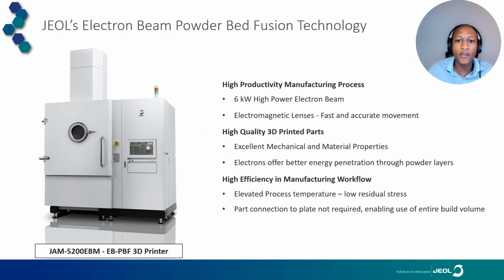So we at JEOL have developed an electron beam powder bed fusion machine called the JAM 5200. It is a high productivity, high quality, and high efficiency manufacturing process. We use a 6 kilowatt electron beam in our process, and we move our electron beam via electromagnetic lenses, which results in a very fast and accurate beam speed and beam control. Our process is able to achieve excellent mechanical material properties while maintaining an excellent density in our melted parts.